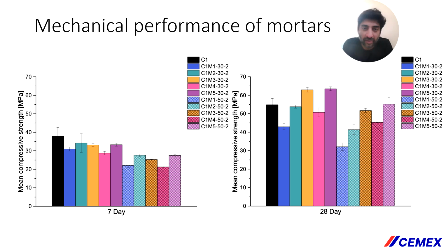Okay, the mechanical performance of mortars was evaluated at 7 days and 28 days at both 30% and 50% replacement levels. The 30% calcined clay blends showed 7-day strengths which were about 10 to 25% lower than the reference, and 50% calcined clay blends were about 30 to 45% lower than the control at 7 days. But notable strength gain was observed between 7 days and 28 days. The strength data partially agreed with the R3 reactivity test. Calcined clays M3 and M5 were found to be the second most and most reactive, respectively, and also performed the best in terms of compressive strength at 28 days at both 30% and 50% replacements.